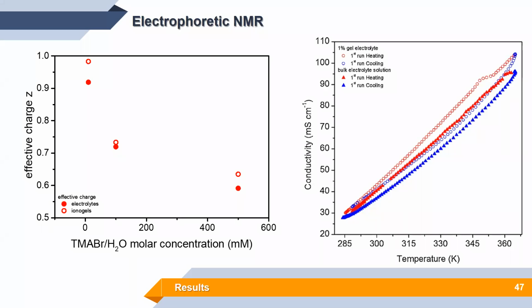And what occurred was that in the gel phase, the effective electric charge of the tetramethylammonium cation was higher than in case of the pure electrolyte, which is the solid dots here. And the gel is the open circles. So this gives us very important information. What is the reason for the higher electric charge is still an open question, but definitely it can increase the overall conductivity of the whole system.